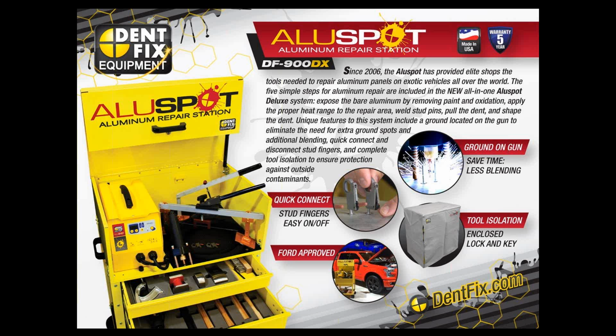Now, how do you heat it up? Well, again, remember, aluminum melts at 1100 degrees. If the technician is not paying attention and he uses a torch, he can easily exceed that and put a hole into it by melting it. So we do recommend using a heat gun. And I have mentioned the digital set temperature one with the temperature range on the back. Currently, the only one I know of is provided by Wagner. That does come with our aluminum repair station.